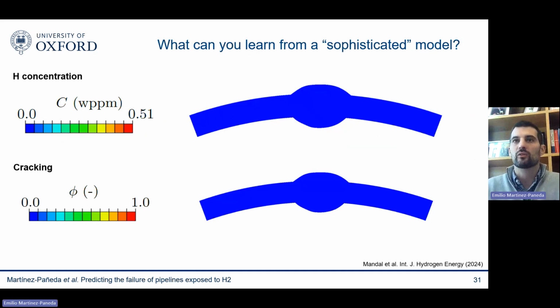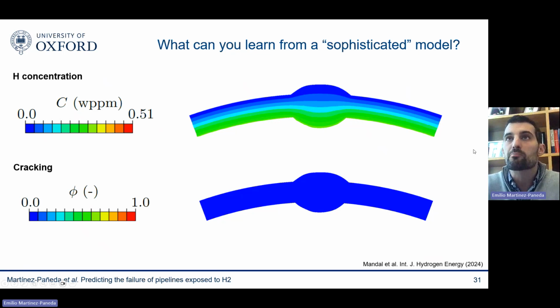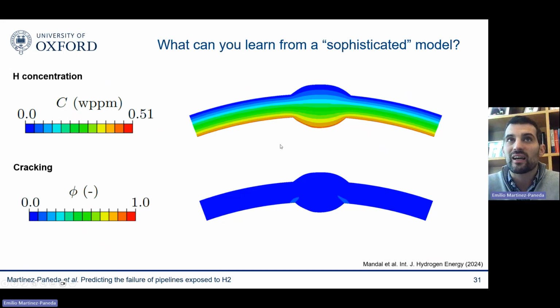Once you have your residual stress distribution and your material property distribution, then you expose your pipeline to a rising hydrogen pressure. And you can see that the hydrogen is increasing. Eventually, when you reach a critical hydrogen pressure, you will see that a crack grows. So you can quantify the critical hydrogen pressure at which your pipeline failed.